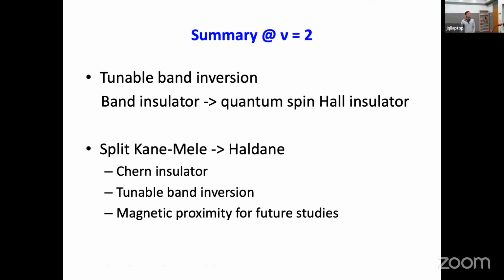Thanks. Okay. So a quick summary of what happened at nu equals 2, which is mostly single particle physics. I hope I convinced you that we have demonstrated tunable band inversion that makes the system a quantum spin Hall insulator. And then by applying a small magnetic field that breaks time reversal, you can split the Kane-Mele system into a Haldane system that produces a Chern insulator with a quantized Hall effect. And it would be interesting to really push to the zero magnetic field limit, if we can proximitize the material to a magnetic material, or for instance, shine circularly polarized light or something, to split the Kane-Mele system and produce the Haldane-Chern insulator by finding some other ways to break time reversal.